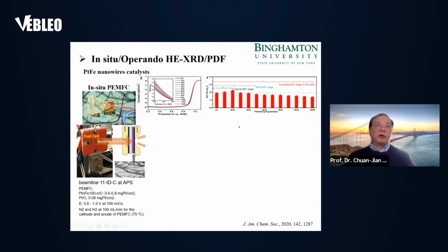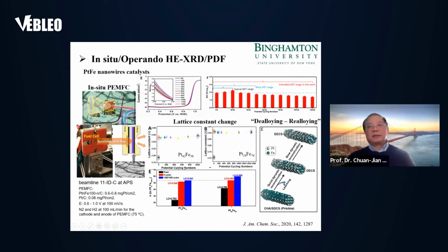Then we loaded the nanowire catalyst in the fuel cell and looked at the lattice parameter change. One thing we noticed here is that they never go to phase segregation. They also, as I illustrated in the previous slide, undergo the de-alloying and re-alloying process. This process allows the nanoparticle to achieve restructuring, de-alloying and re-alloying, as illustrated in the far right panel. Okay, so in the process you subject it to de-alloying, leaching of the base metal ion, then you have re-alloying of the remaining metals inside the nanowire, and ultimately reach a very, very stable state.